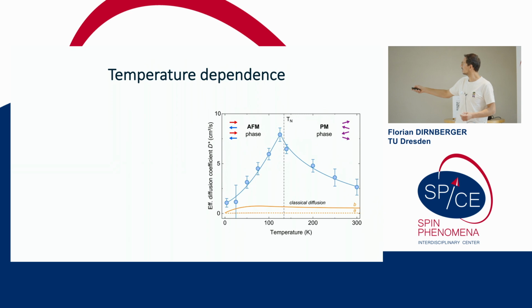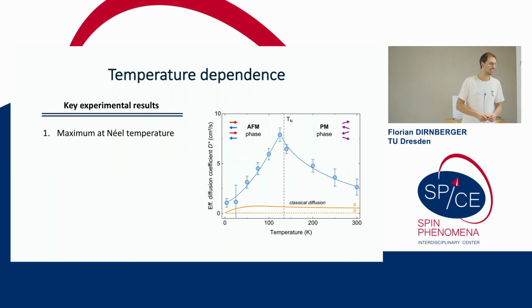So when we track this effective diffusion coefficient, we see this increase towards the Néel temperature, and then there seems to be a maximum in the vicinity of the Néel temperature, and then it continues to decrease as we go to higher temperatures. So it looks like, particularly at the Néel temperature, the excitons move the fastest away from the excitation region. So this is the first key result of this experimental study. We see this maximum at the Néel temperature.